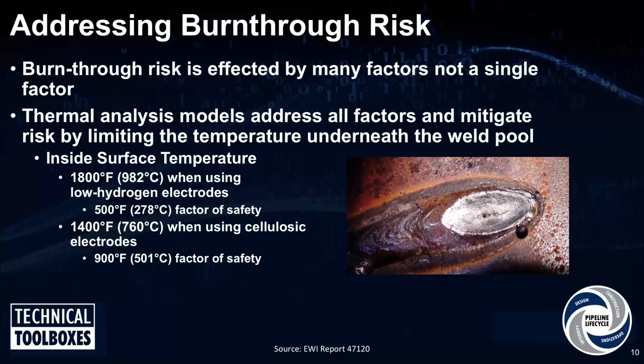So the limit that most weld models, including the PRCI model, base their burn through risk on, there's two values, and they're tied to the welding electrode used. The first limit is 1800 degrees F, and that's the maximum inside surface temperature when using a low hydrogen welding electrode. And now if you want to do an in-service weld with a cellulosic electrode, their inside surface temperature limit is 1400 degrees F.